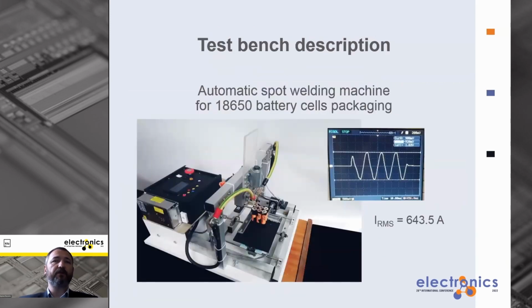Okay, and so in order to investigate an influence of the welding parameters of the welds, the automatic spot resistance welding machine was designed and constructed. As you can see on the presented slide, it has a function of setting two welding time pulses or turning off the second pulse completely. The RMS value of the welding current was measured as about 643 amperes.